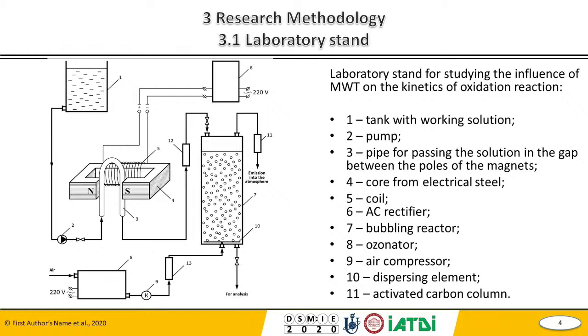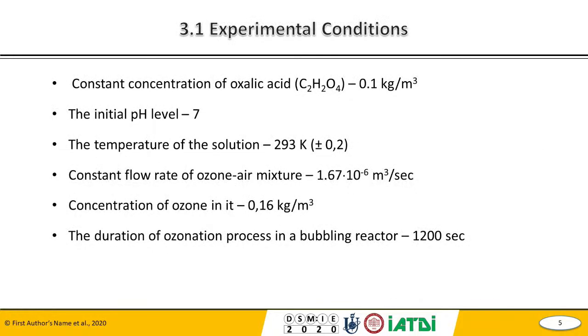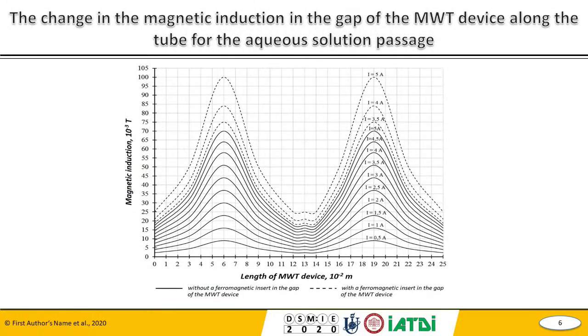Next slide. You can see here the general experimental parameters of the working solution and other parameters of the experiment. The inhomogeneity of the magnetic field in the magnetic devices was provided by the movement of the aqueous solution in the magnetic field, with a variation in magnitude from minimum to maximum along the trajectory, and this trajectory looks like depicted on the next slide. You see some waves that illustrate the changes in magnitude.